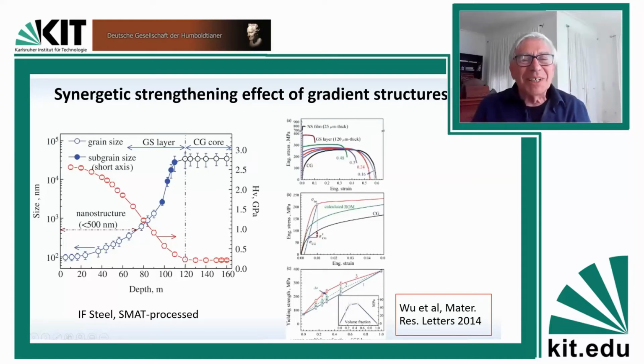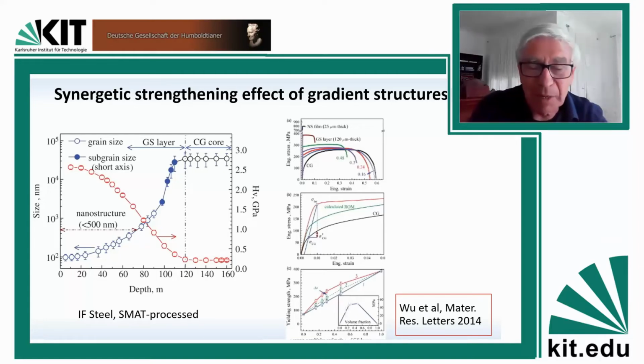And if you add up the loads that are carried by these layers using the so-called rule of mixtures, if this is the coarse-grained one material, you would get this green curve. In reality, in experiment, you get this curve, the red one. That is, you get much more than the additive contribution of the layers would produce. That is, there is some synergistic effect which is due to this gradient structure. And there are now various efforts to understand exactly how that works, how a gradient plasticity theory should be designed to explain this. But the experimental outcome is quite appealing. It is an increase of the strength of the material, actually without loss of ductility of the material.